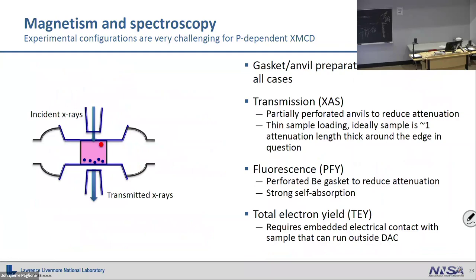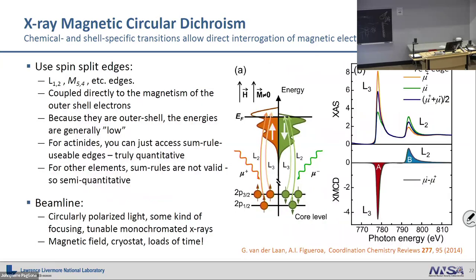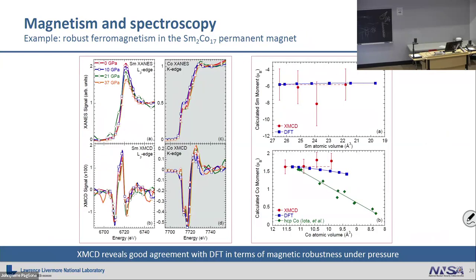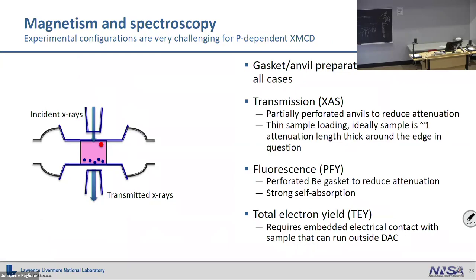So this one's a little tricky with a DAC too. The reason it's tricky is because you have to go to all of these site-specific, these chemically specific X-ray edges. So if I'm doing this, I need to be able to excite the iron atom here. That's a very specific edge that I have to go to. In this case, it's an L2 or an L3 edge that I have to choose. And so now I have to pick that energy. It's not a variable energy, and I need to get that through the DACs. So something like a rare earth, that might be at 5 kilovolts. And I told you that diamond stinks below 6. It's very hard to do measurements down there.